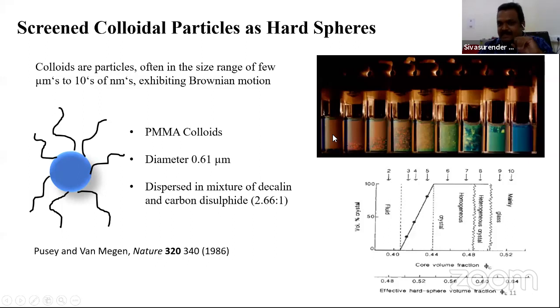Which indicates that the colloids are completely dispersed in the solvent, and this is a pure liquid, right? And when you start increasing, you can see that there is a small part which is settled at the bottom of the vial, which shows a marble-like feature, right? This marble-like feature is because of the light getting reflected by the crystalline texture which is getting formed. So this is having a fluid-crystal boundary.